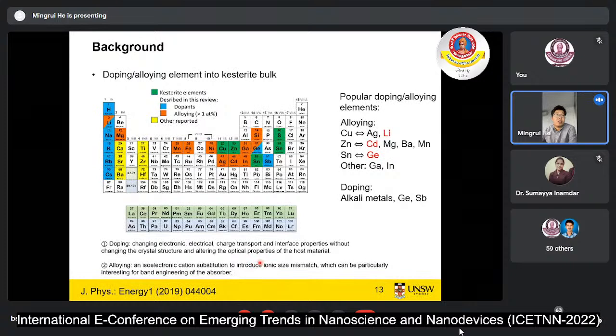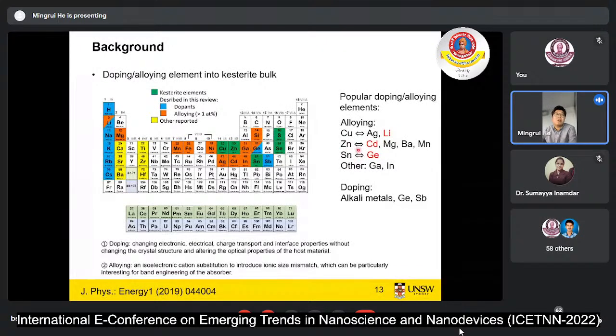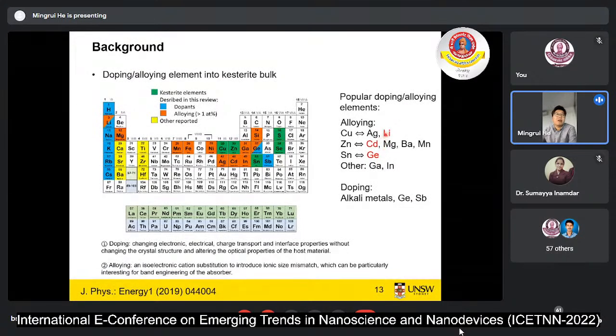So that's my strategy. As we have copper zinc tin, we have many choices to replace these elements. For example, for the copper, we can alloy silver or dope lithium. For the zinc, we can alloy cadmium and other things. For the tin, we can alloy or dope germanium. In CZTS, silver, cadmium, and germanium are the most popular materials that can be incorporated into the kesterite bulk.